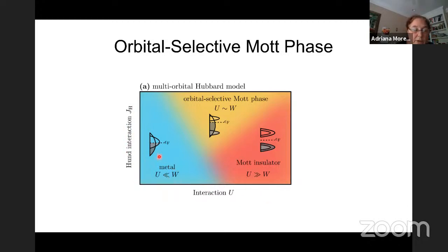At low values of U, the system is metallic with all orbitals participating in the Fermi surface. At large U, compared with the bandwidth, the system becomes a Mott insulator with a gap in all orbitals. But at intermediate values of U, with relatively large Hund coupling, we found this interesting orbital selective Mott phase, in which one orbital becomes a Mott insulator while the system remains metallic in all the other orbitals. Most of my talk will focus on the properties of this phase.